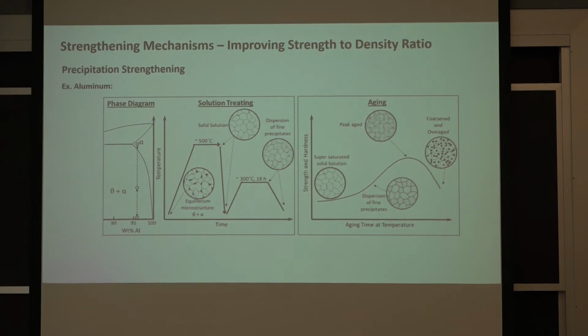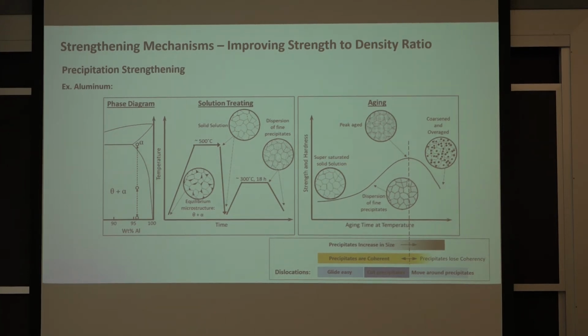You can see I've put that in the bottom of the slide here. As you go, in the third graph, from right to left, you see that the precipitates grow, the coherency of these precipitates goes from being coherent to not being coherent, and then the dislocation moves through that material with a different mechanism. The mechanism in the middle is the preferred one. That's the one that gives you the highest strength.